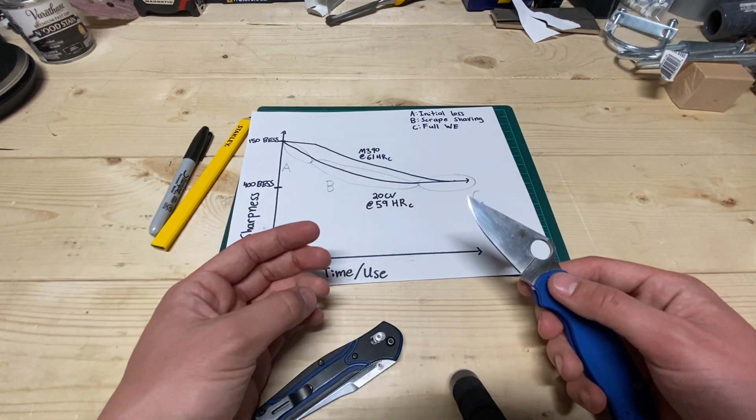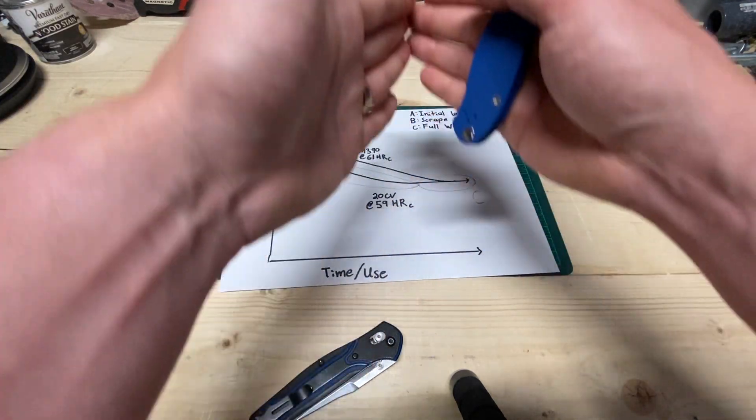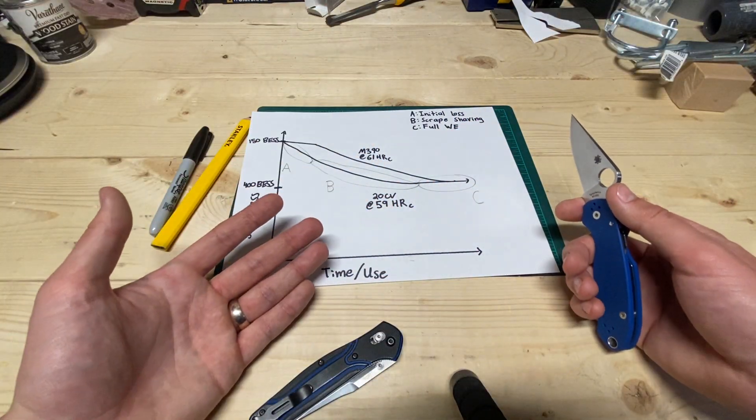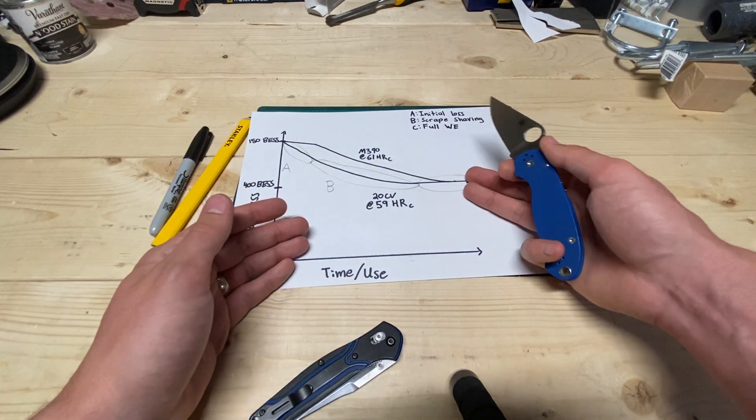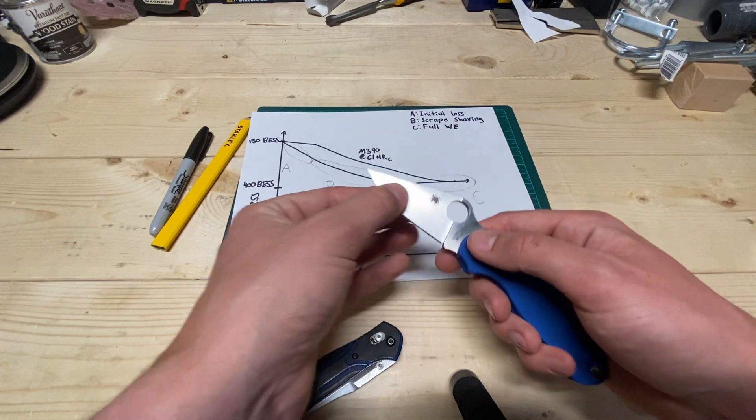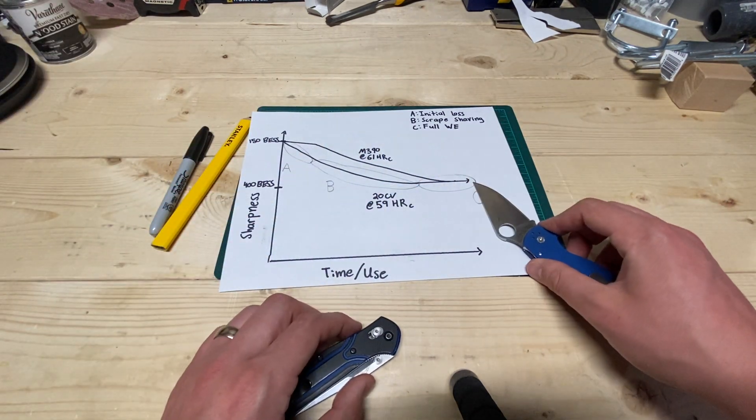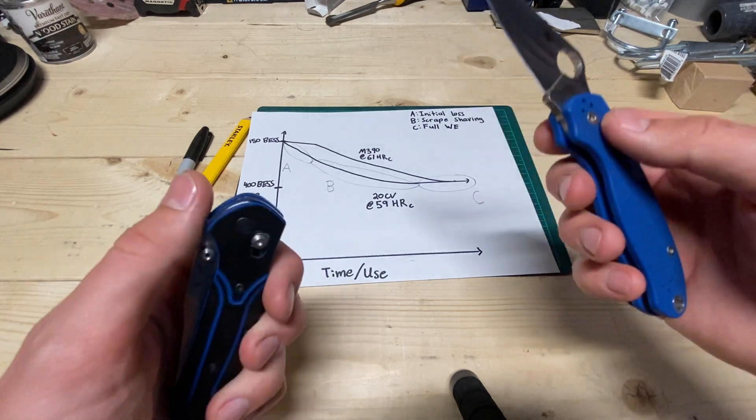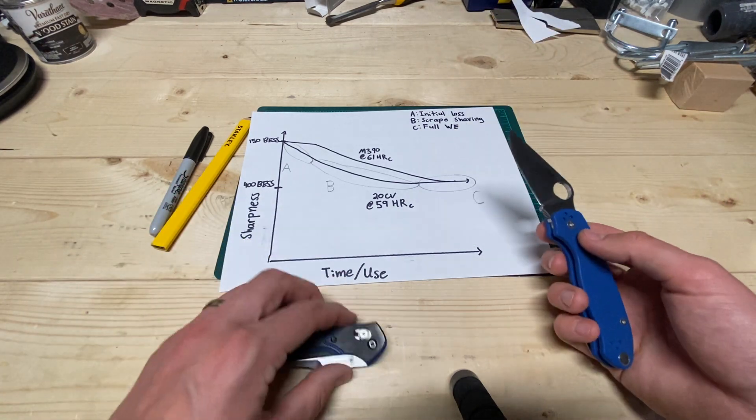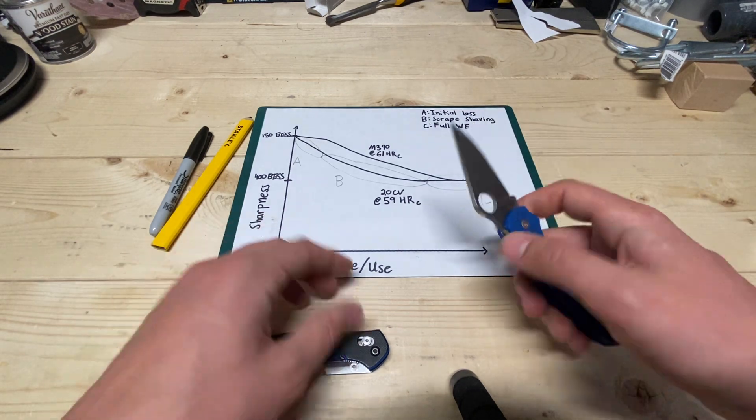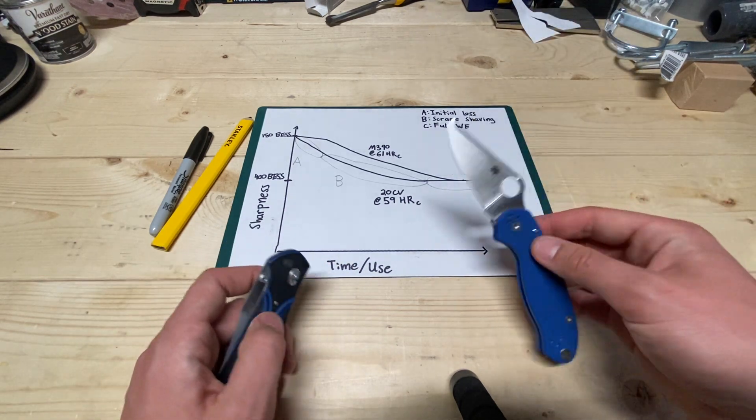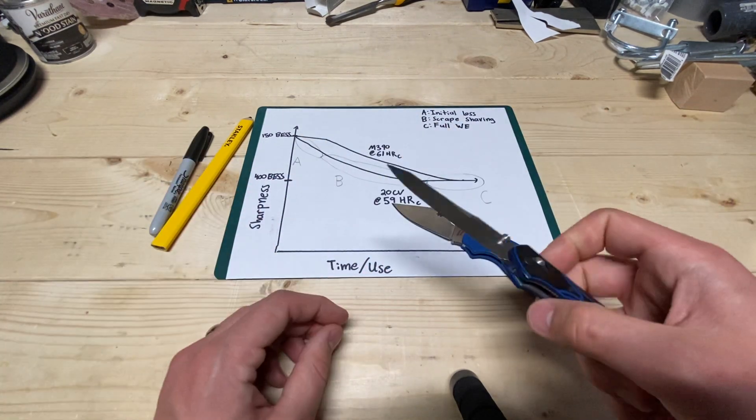And so, what you go from is kind of a real, at the front end, this real fine slice-through bite to what becomes more like a saw. It'll tear through cardboard. It'll tear through the paper fibers. Because it's got those carbides sticking out. And that's what you get in this working edge, where it'll just cut stuff because it's got the serrations, the saw teeth. And that's what you get there.